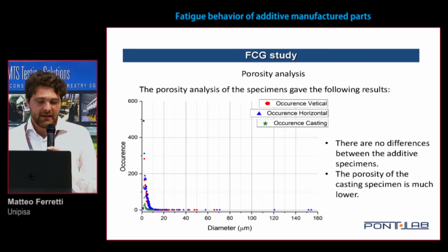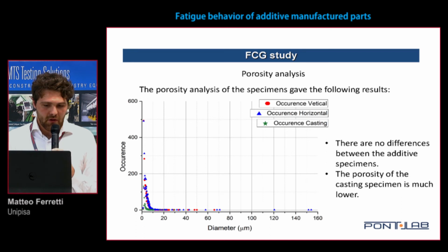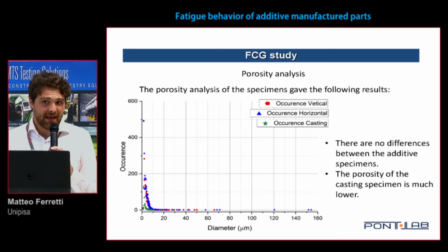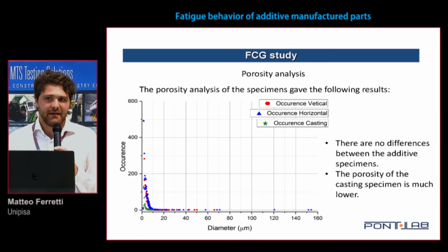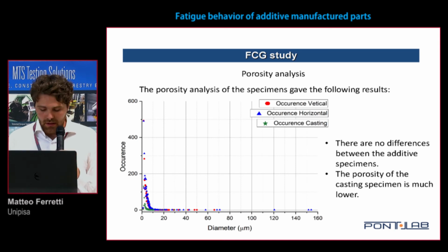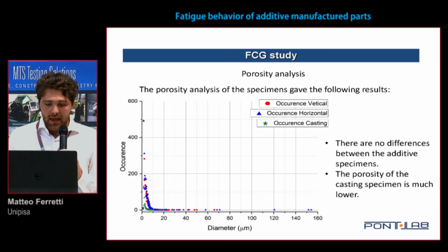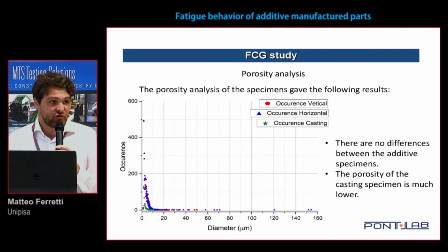After this study, we carried out a porosity analysis. In fact, the presence of porosity is a big problem for additive manufacturing. And as we can see in the picture, between the two types of additive specimen, there is no difference. The porosity is similar. Instead, the porosity of the casting specimen is much lower.